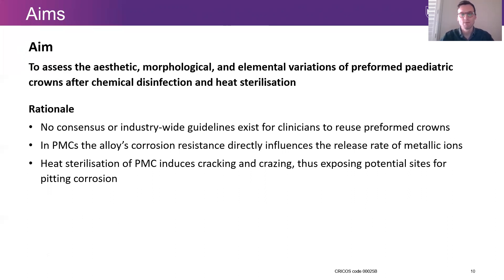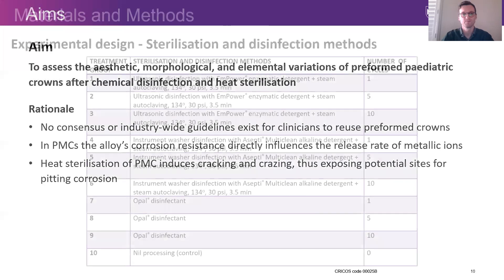One paper found that in preformed metal crowns, the alloys' corrosion resistance directly influences the release rate of metallic ions. Another paper found heat sterilisation of preformed metal crowns induces cracking and crazing, thus exposing potential sites for pitting corrosion to occur.